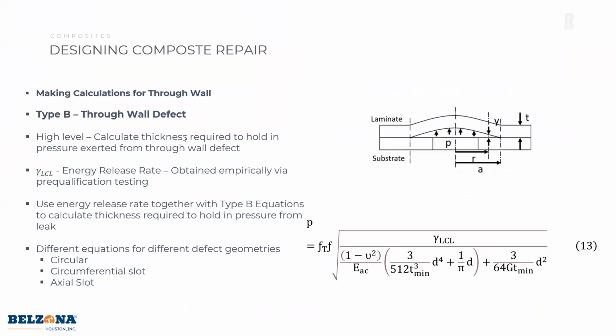Next, if you have a leak, you want to design: how much thickness do I need to contain a leak? This is done via several equations. We have equations for circular holes, for circumferential slots, for axial slots. The main inputs to the equation are going to be your pressure and the size of the defect. And then we use the testing information we have, plug it into this equation here, and figure out how thick the repair has to be.